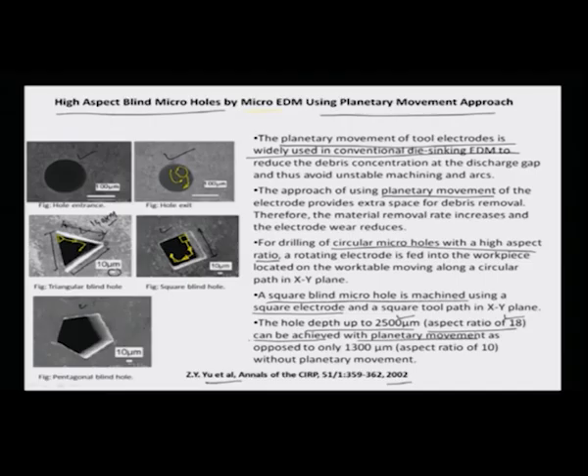So if you had no planetary movement, for example, if this same process would have been produced by a normal electrode of the same size as the hole, the aspect ratio would then come to about close to 10. Okay. So in a way it illustrates what the planetary motion does in terms of debris removal, where the activity can be prolonged over a higher amount of depth, so that the aspect ratio can increase accordingly. So in 3D micro machining, particularly when we are talking about large aspect ratio structures, definitely planetary micro EDM is a very good strategy to manufacture at this particular length scale.